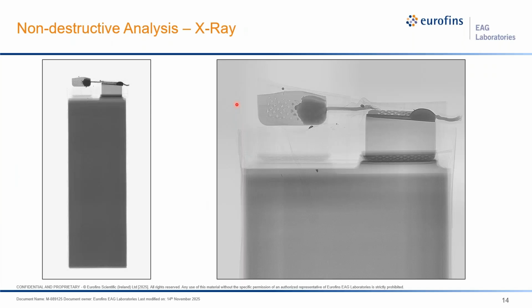So this is the image from the 2D X-ray. Of course, when we first get the device, a failed device, for example, like a phone or a tablet battery that is severely swollen, then we look for any external mechanical damage or thermal damage that might be happening for the device, because these can also initiate the failure mechanism for the battery. But if you do not see anything with our naked eye, then 2D X-ray is definitely most helpful.